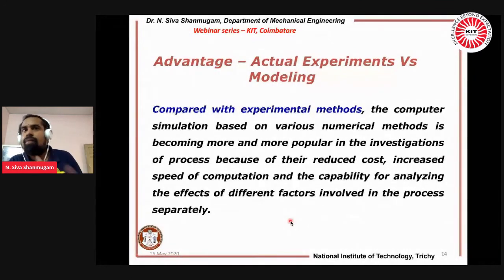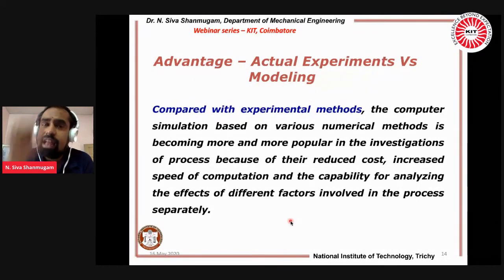Second, sir, I am not getting any analytical equation. Then do the actual experiment, do the laser welding, cut the specimen, metallographically prepare the specimen, etch it, polish it, and reveal the macrostructure to get the bead width as well as the depth of penetration.